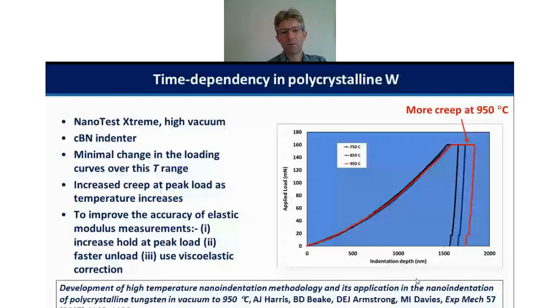So the next thing that we need to worry about essentially is the enhanced time-dependent deformation that we see at high temperatures. This, again, is an example on a polycrystalline tungsten sample. These are data taken in high vacuum. And in the temperature range 750 to 950 degrees, what's interesting is that this material doesn't particularly soften over that temperature range. So the loading curves, you can see, are almost superimposed.